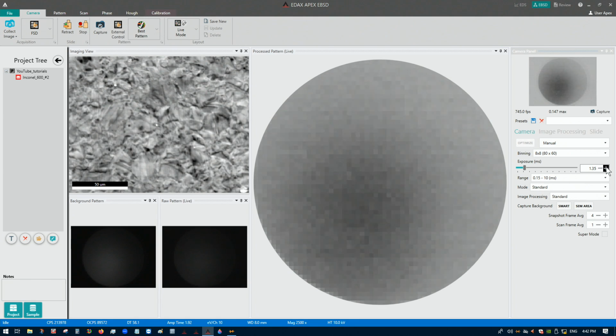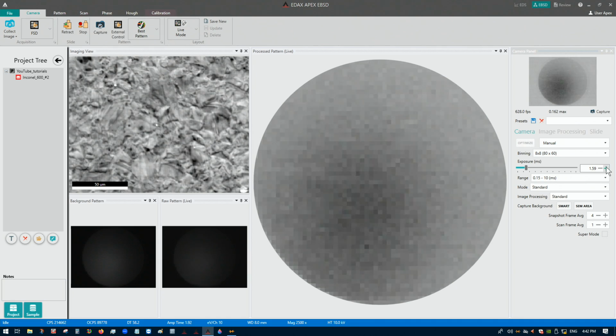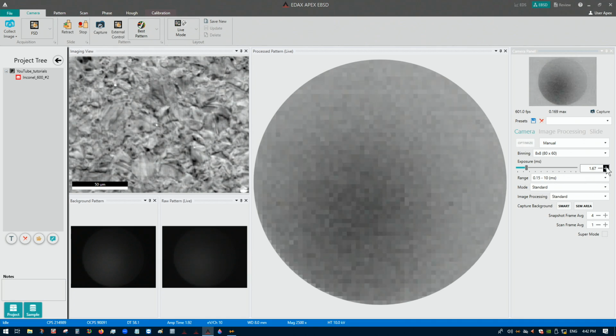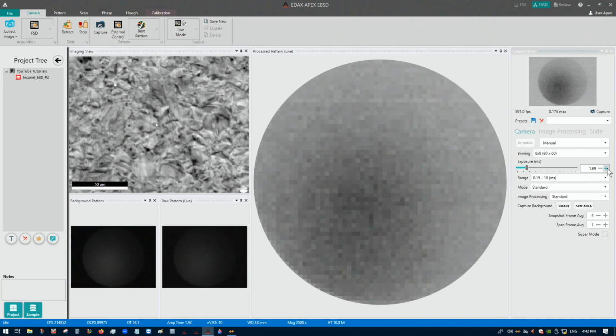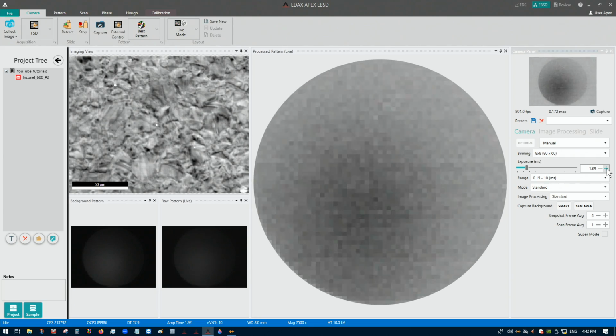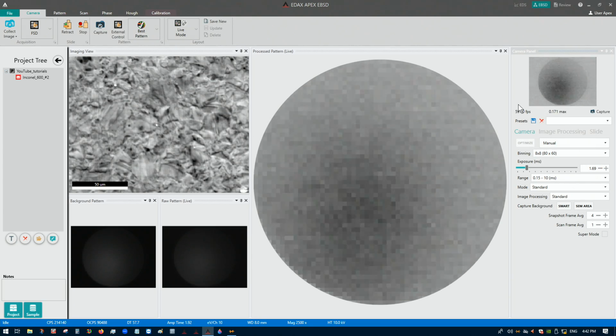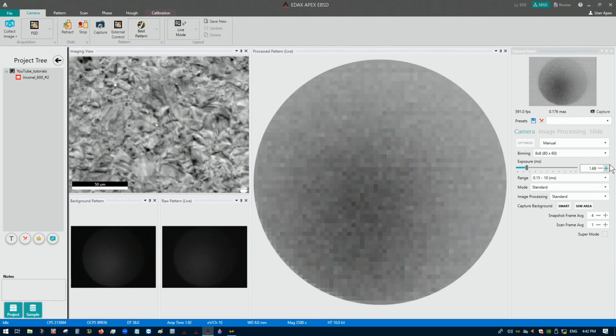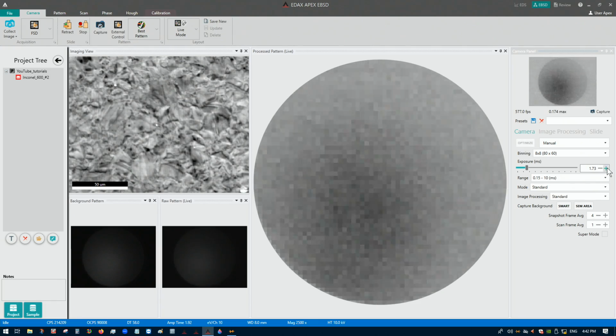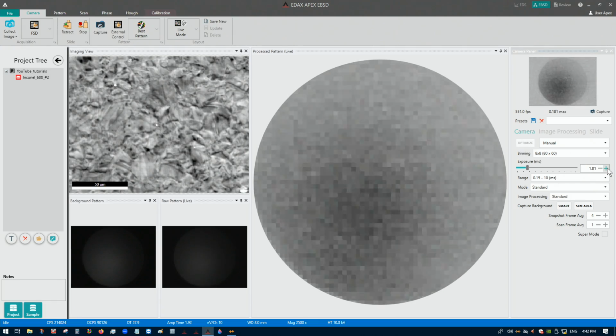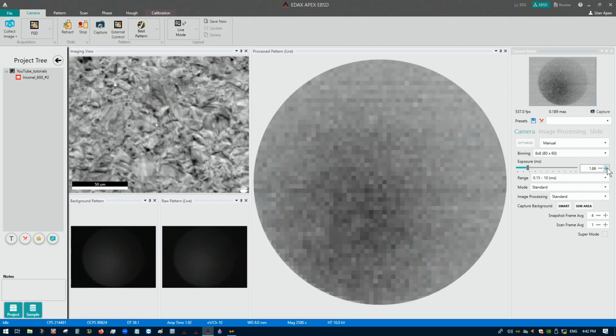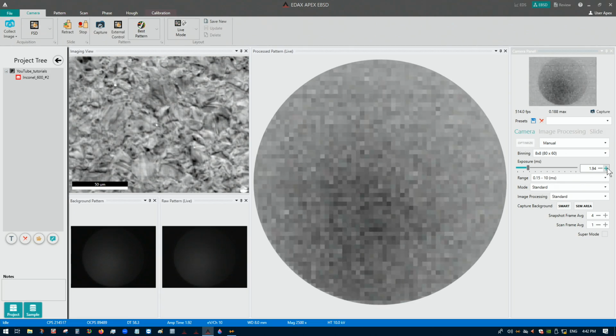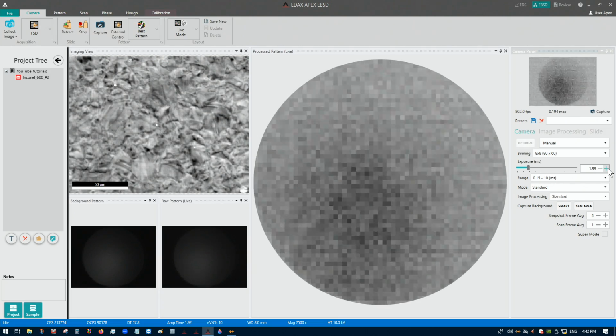So now what I find is that an intensity fraction of 0.1 or higher will usually give usable patterns. The more the better in terms of signal to noise, right? So there's a benefit there, but of course, the higher you make this or the lower you make this, the slower your data acquisition is going to be, okay? So let's put this at about 0.2, which should give us around 500 frames a second. We'll leave it at 500 frames a second.